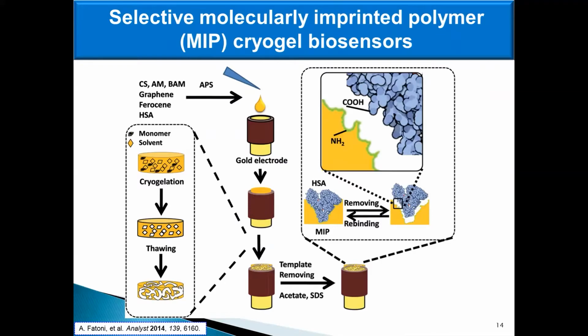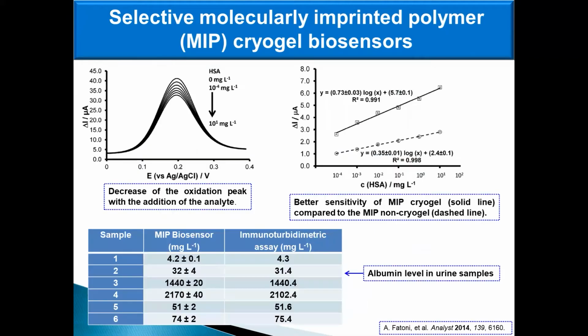Using the molecular imprinting strategy, a highly sensitive and selective protein-imprinted cryogel for determination of albumin in urine samples was fabricated. The molecularly imprinted cryogel was formed by adding chitosan, acrylamide, bisacrylamide, graphene, tyrosine, and albumin onto a gold electrode and incubating at -20 degrees Celsius. After removing the template, the specific imprinted surface on the cryogel was used to detect albumin via a redox mediator, ferrocene, also entrapped in the cryogel, using differential pulse voltammetry. The detection of the albumin was based on the oxidation of the ferrocene entrapped in the cryogel matrix.